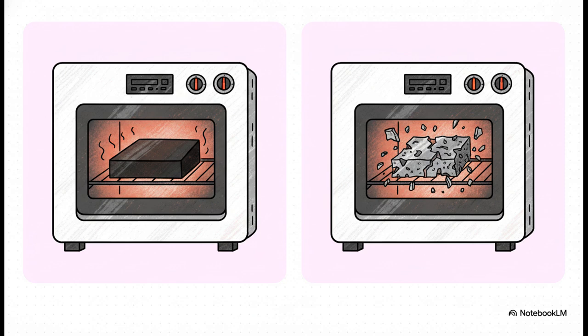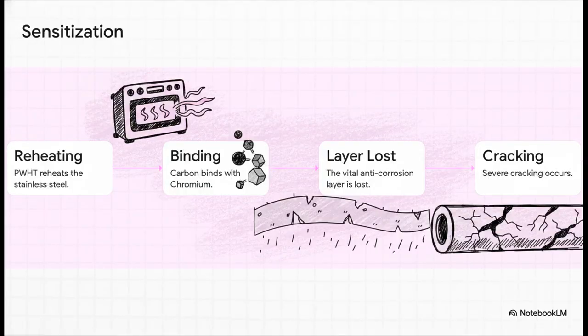Carbon steel absolutely loves heat treatment. It needs PWHT to relieve stress safely. But if you take a vessel made of stainless steel and try to put it through that exact same baking process, you are going to completely ruin it. For stainless steel, PWHT triggers this terrifying chemical breakdown called sensitization. It essentially destroys the metal's natural ability to fight off rust and corrosion. Let's break down exactly why this happens, step by step, so we can see how stainless steel loses its superpower.